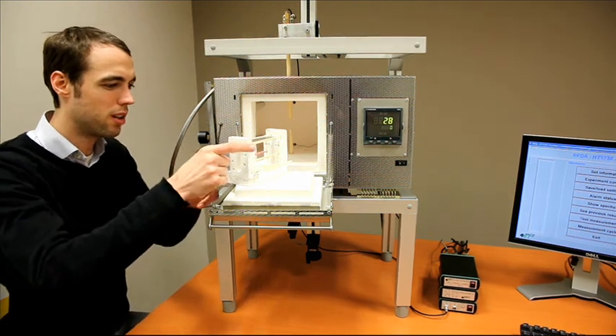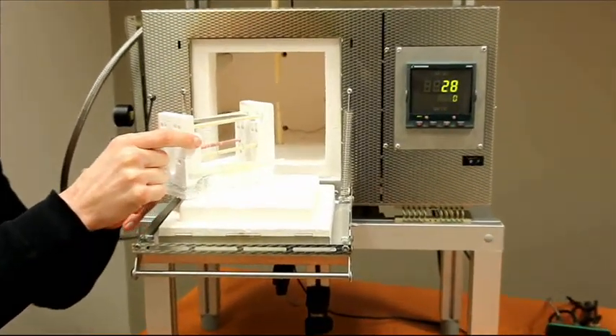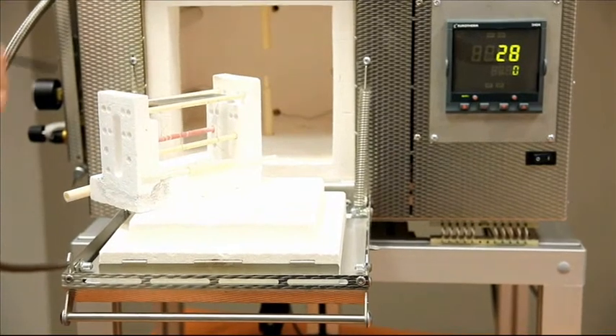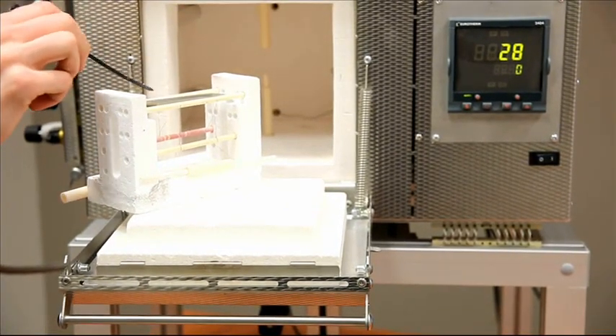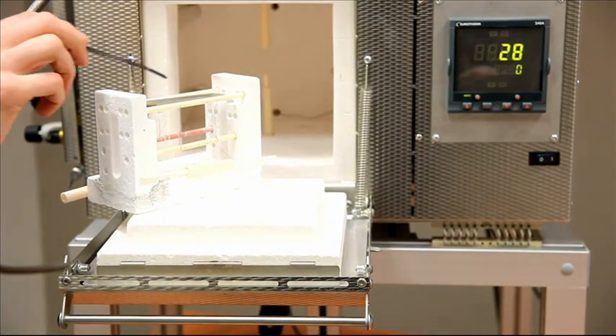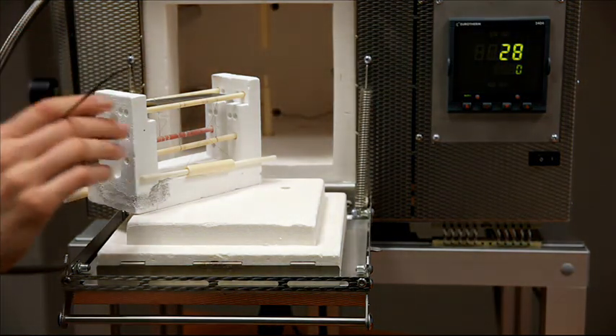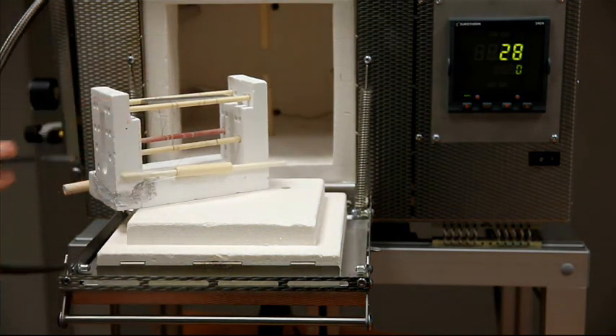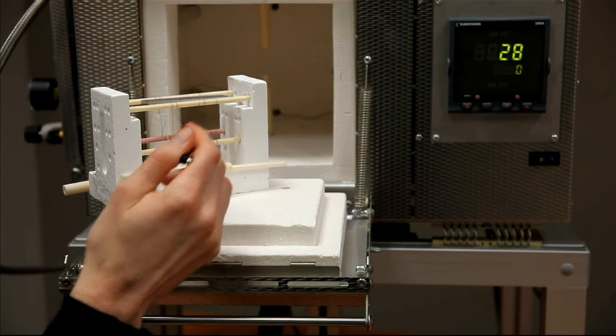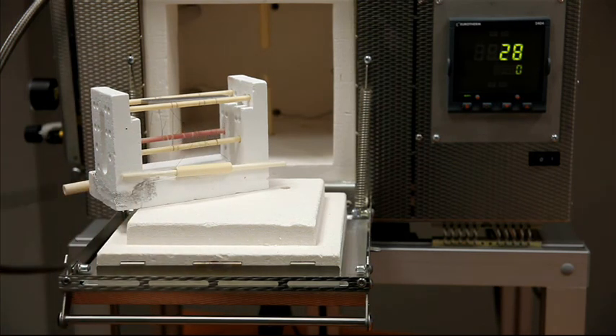First, let's have a look at the measurement setup itself. Here we're going to measure a metallic rectangular bar. The sample is supported by two platinum rhodium wires, and the rest of the setup is made out of aluminium oxide. So the measurement setup itself can handle temperatures well over 1000 degrees Celsius.